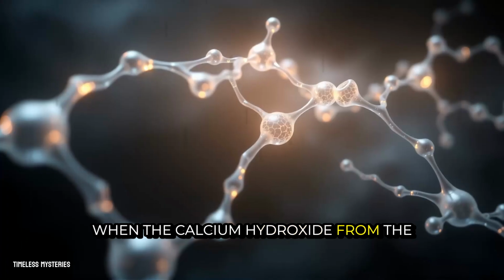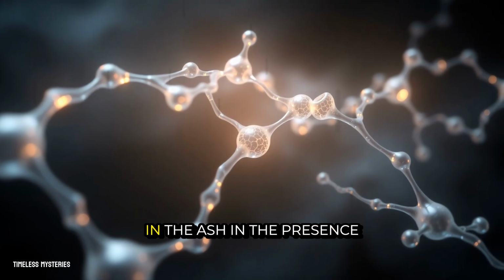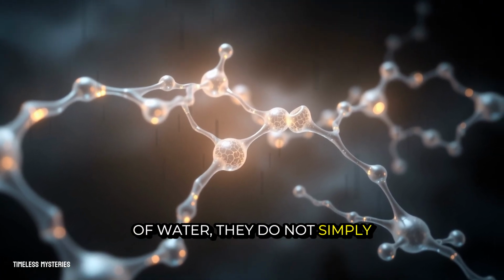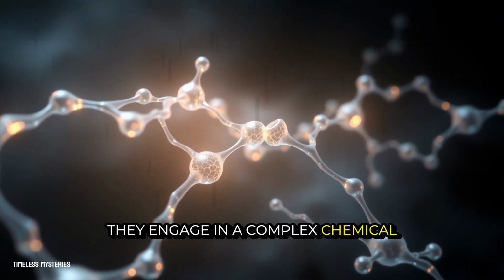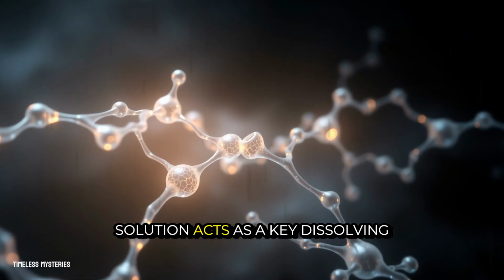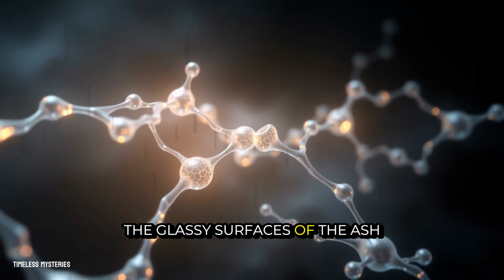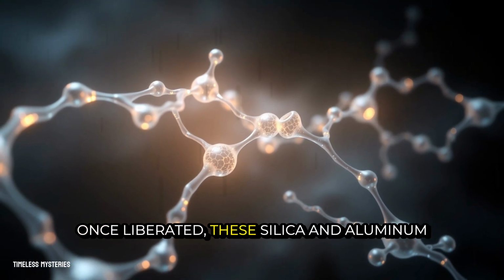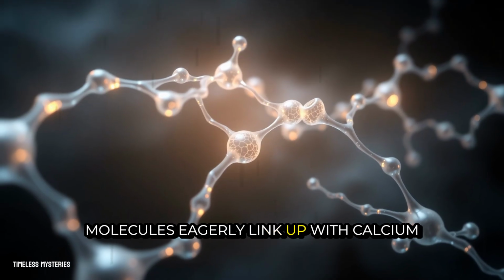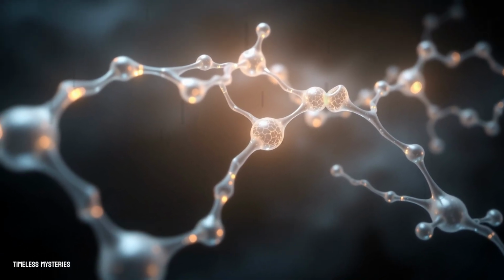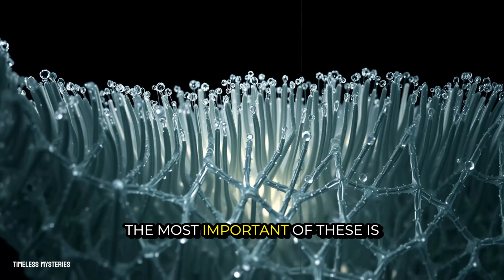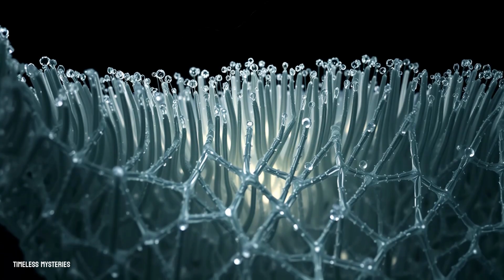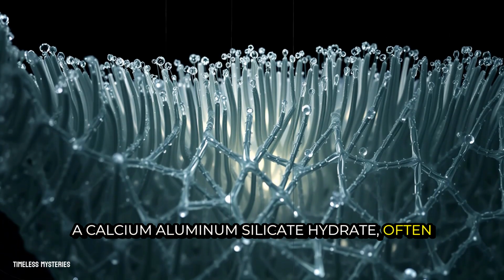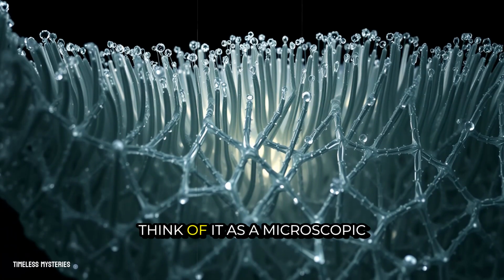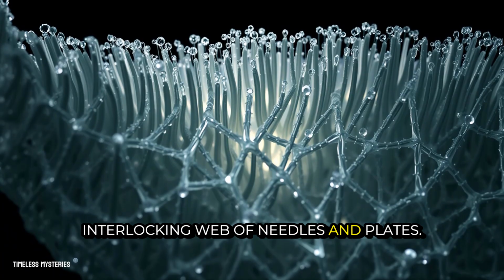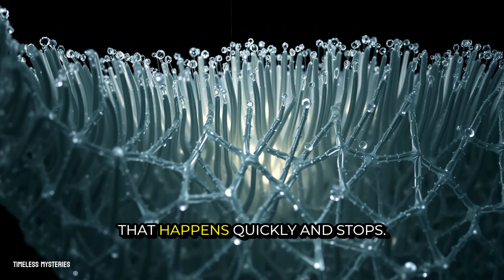When the calcium hydroxide from the lime meets the silica and alumina in the ash, in the presence of water, they do not simply sit together. They engage in a complex chemical dance. The high pH of the lime solution acts as a key, dissolving the glassy surfaces of the ash particles. Once liberated, these silica and alumina molecules eagerly link up with calcium and water molecules from the lime. The result is the formation of new, incredibly stable crystals. The most important of these is a calcium-aluminum silicate hydrate, often called CaSH for short. Think of it as a microscopic, interlocking web of needles and plates. This is not a single event that happens quickly and stops.